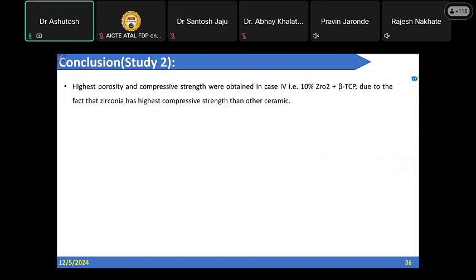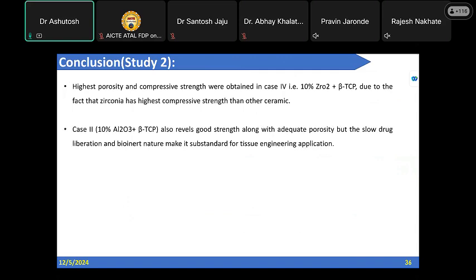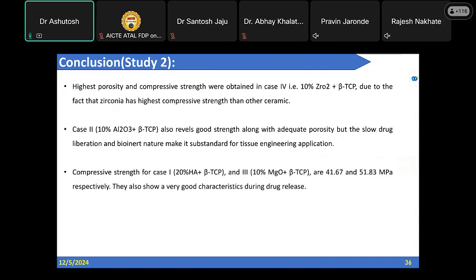So from this study, I concluded that higher porosity and compressive strength can be obtained in case 4, where we are using zirconia 10%. In case 2, we get good strength along with adequate porosity, but slow degradation, slow drug release, and bioinert nature make it substandard in case of tissue engineering.